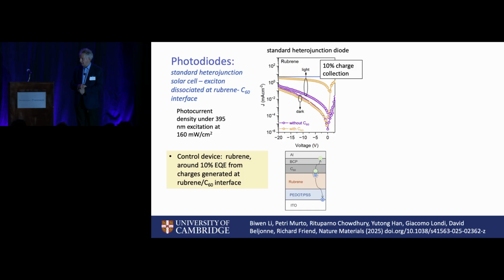And we can. We better start with a control device, which is a heterojunction between rubrene and C60. The rubrene is an electron donor. The C60 is an acceptor. And if we just make a layer-by-layer device, we get about a 10% charge collection because only light absorbed quite close to the interface works.